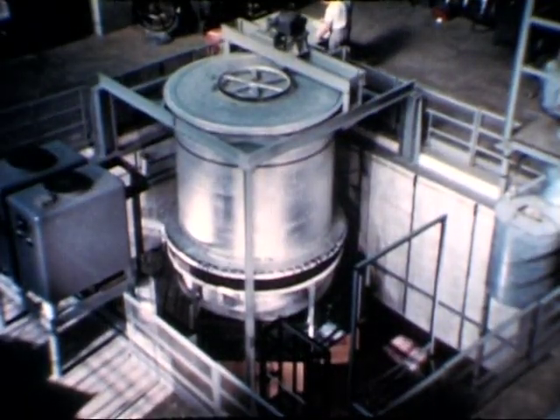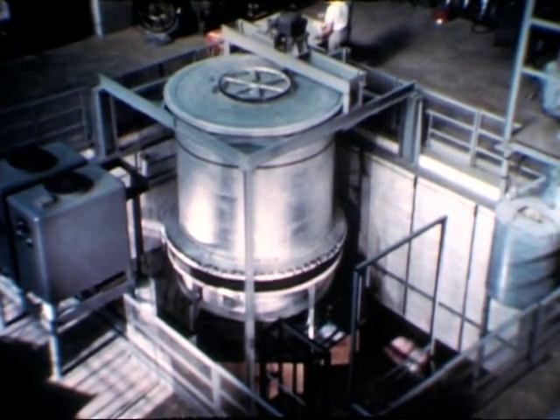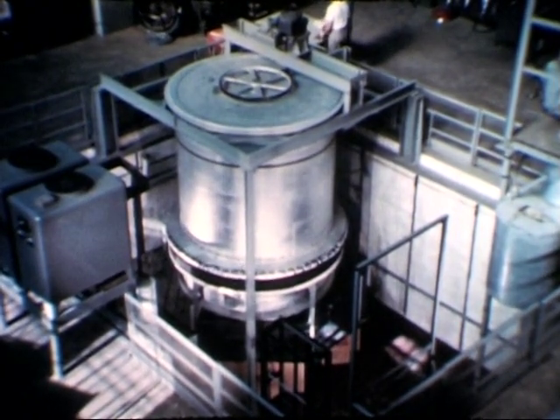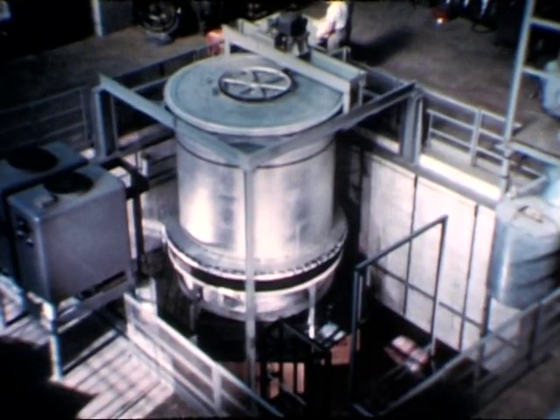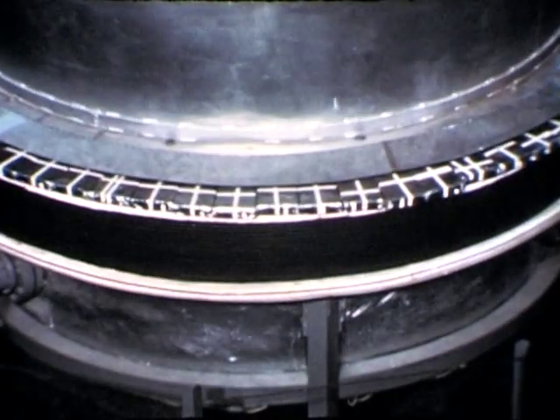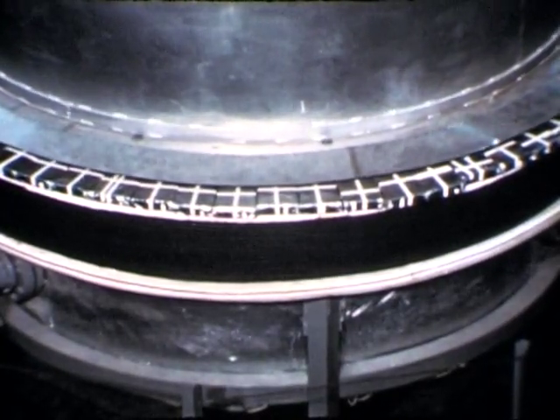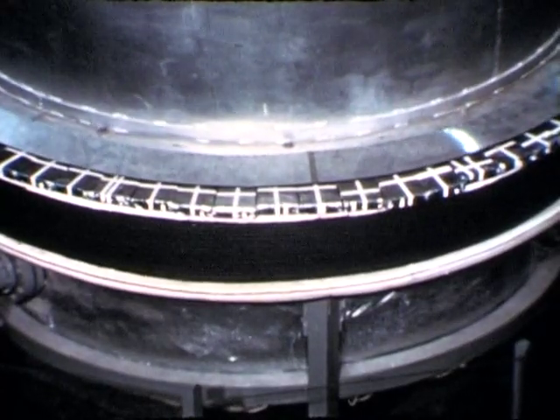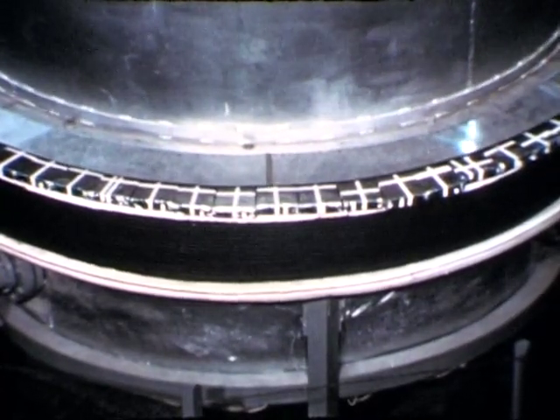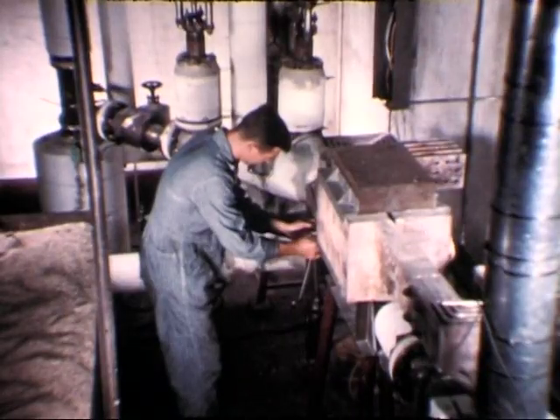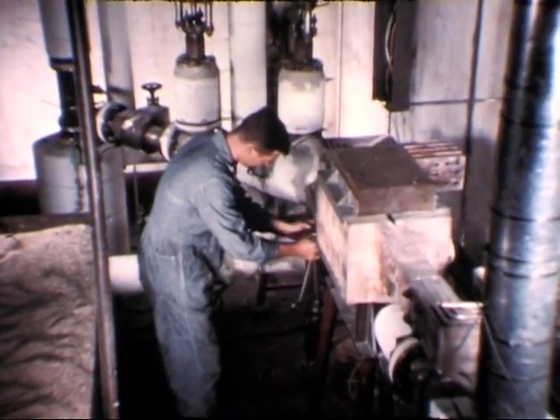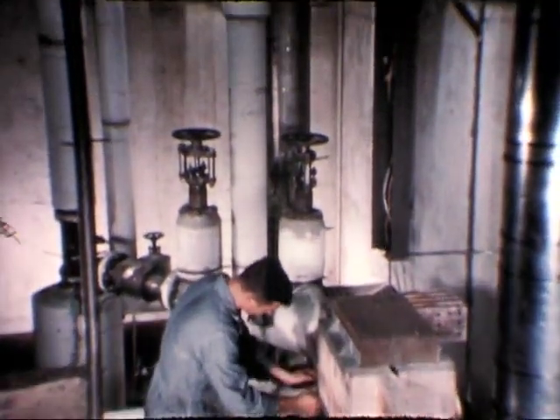A rotary reactor plug using tin bismuth as the sealant has proved difficult to make absolutely gas-tight. Although sealed when the alloy is molten, further study is required to determine the nature of the small leakage when cold. Sodium piping system components have been developed for flows up to 5,000 gallons per minute and temperatures to 800 degrees Fahrenheit.